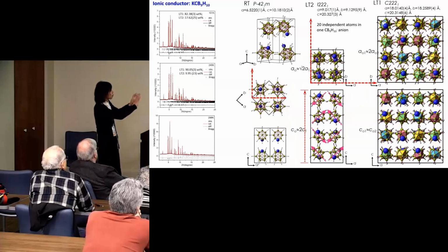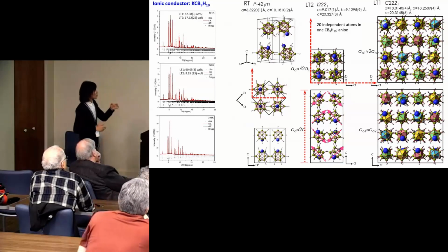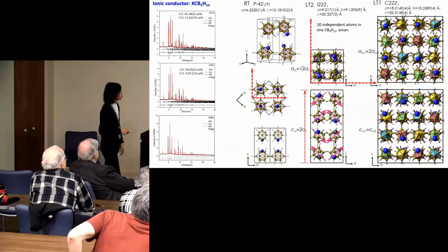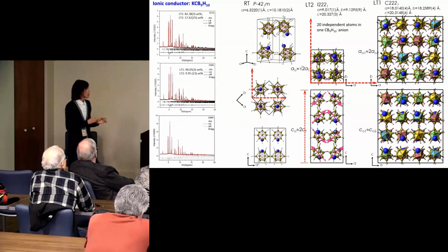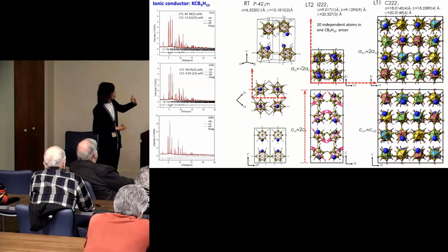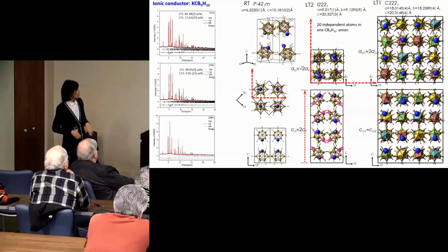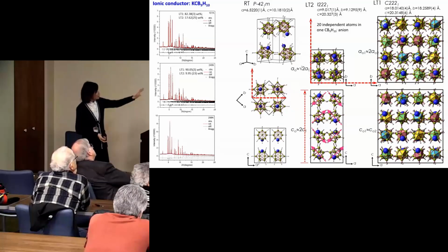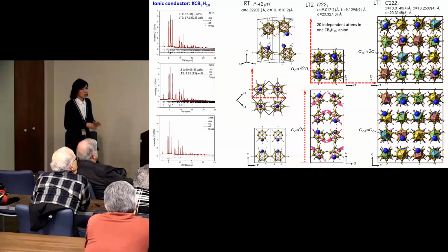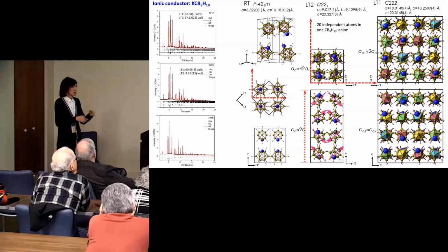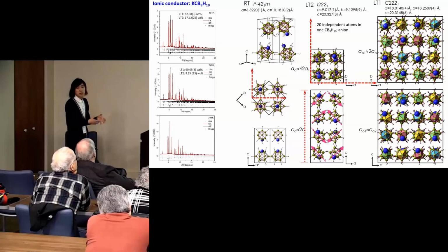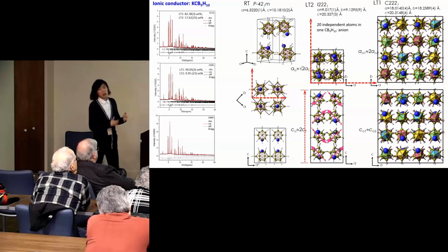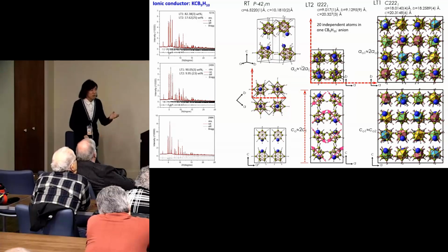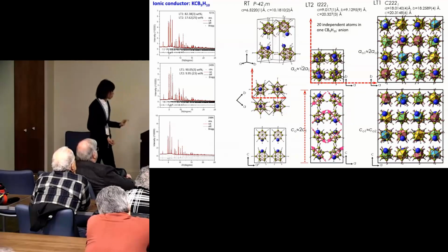I don't want to go into details about how the phases convert to each other. I just want to mention, for example, for low temperature phase 1, it has 4 independent CB9H10 ions at general sites. And we know each anion has 20 atoms, so we will have 80 independent atomic positions. And then we also have 4 independent potassium. So the total number of parameters that need to be refined will be enormous. So again, with the help of rigid body constraints provided by GSAS, we were able to refine those structures just based